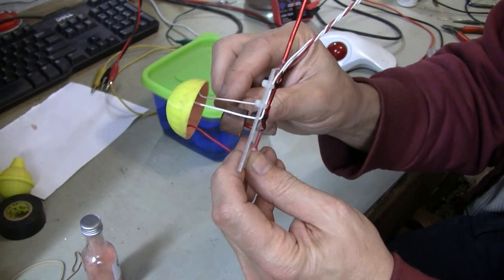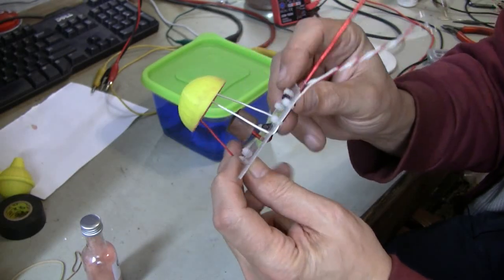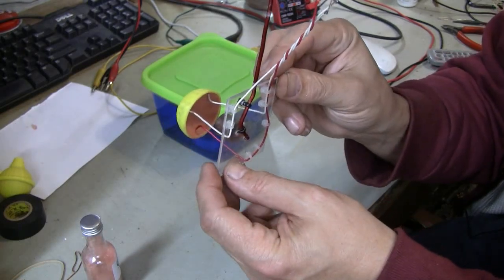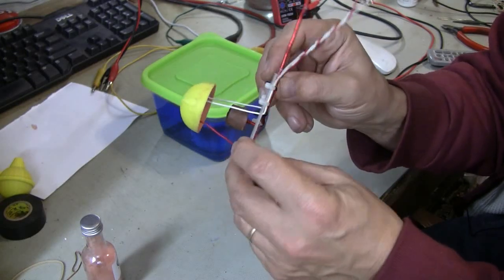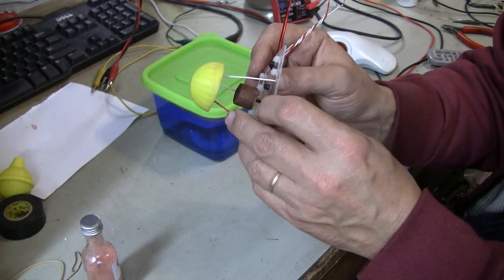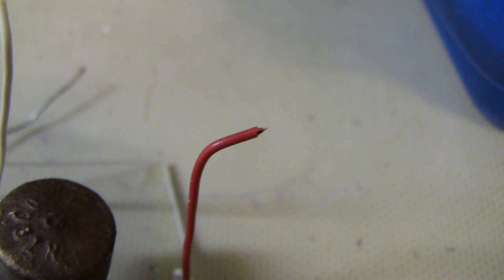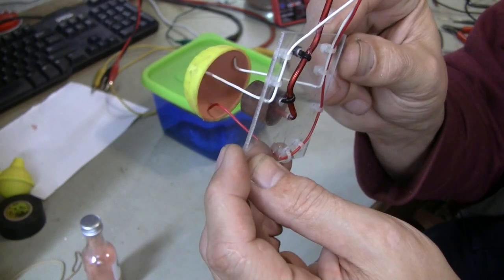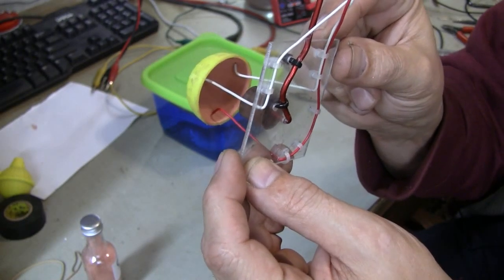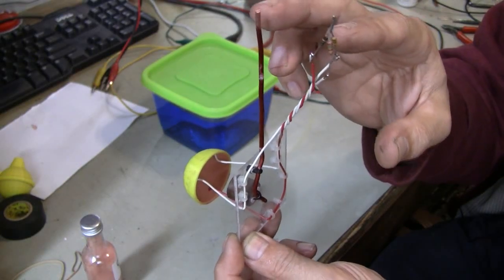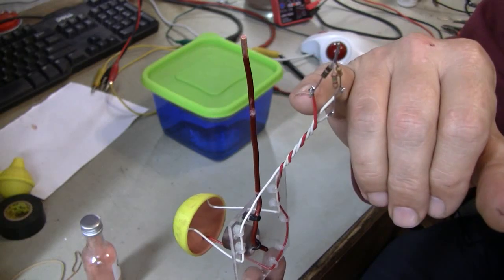Now one of the key elements to a successful plating using this method that I found was start slowly. In the previous video I showed you the way the tips were cut. I only expose a very tiny amount of copper at the tip of the electrodes that are touching the inside surface of the half sphere. That's because that's the part that immediately starts to conduct when you apply voltage to the two terminals on the electroplating jig. Also notice that I have voltage dividing resistors here that give me a very even current being fed to each of the three tips.